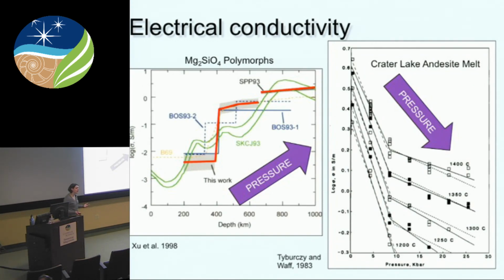Electrical conductivity also shows opposite behavior for crystalline and liquid silicates. So for crystalline silicates, as you increase pressure, the models, most of the lines back here are models. Here's the actual experimental data highlighted in red. So we have conductivity as a function of depth. And as you increase density, as you compress a crystal structure, even going through phase transitions, what you see is an increase in the conductivity.